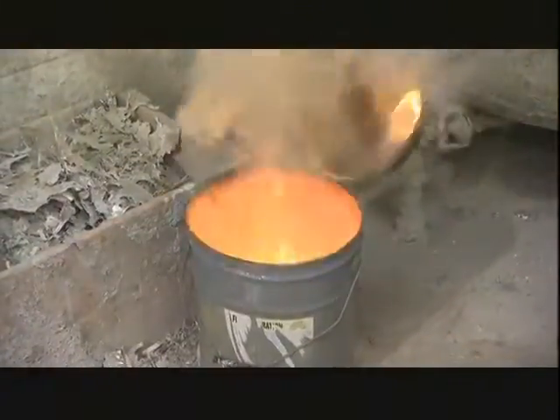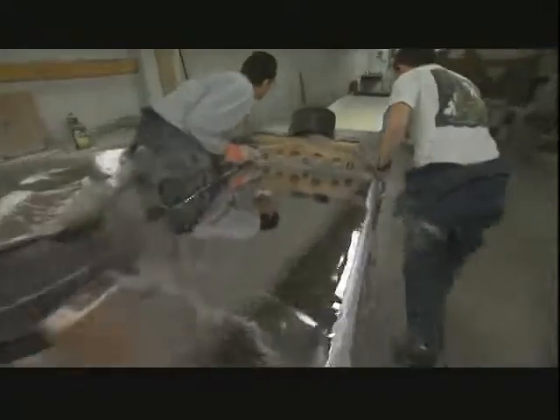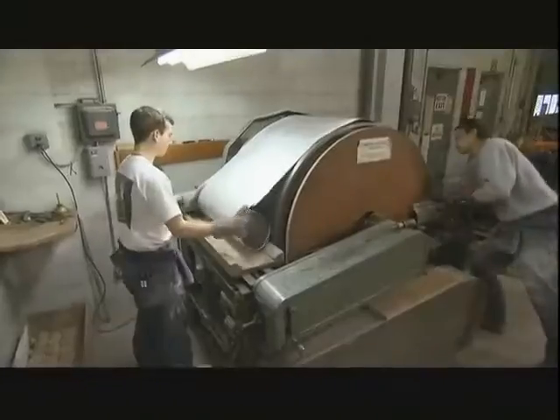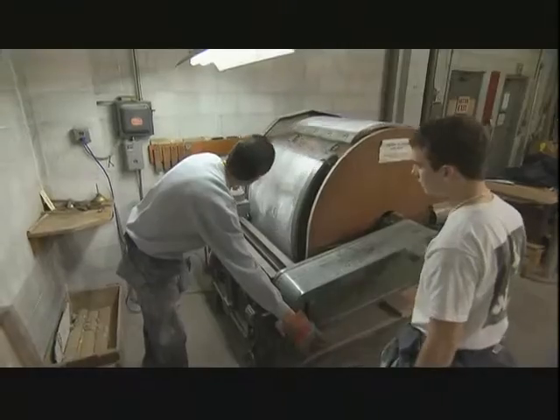After skimming off the impurities, workers let the molten metal cool to about 450 degrees. Then they pour it into a trough and quickly run to the end of a stone table covered with a lid. The sheet solidifies within seconds. As the sheet cools, lead separates from the tin, and spotted metal earns its name. After sheets cure for 2 months to reduce their springiness, workers use a special plane to adjust the thickness.